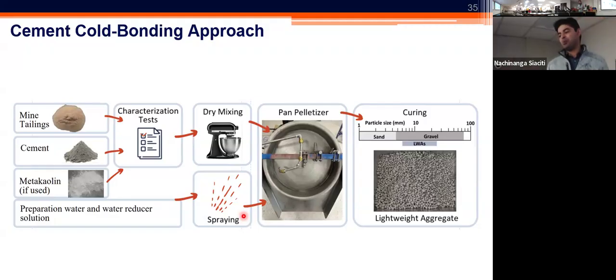It is a fairly similar process, but we believe that this would also have potential for adoption because, first, you don't have any need for alkali activator, which is generally a hazardous type of material. Second, the process of spraying is fairly simple, and you're just spraying water onto an already mixed solid powder of the tailing and the cement. And we have gotten some encouraging results with only using 30% of cement, still 70% of the tailings used for this application.